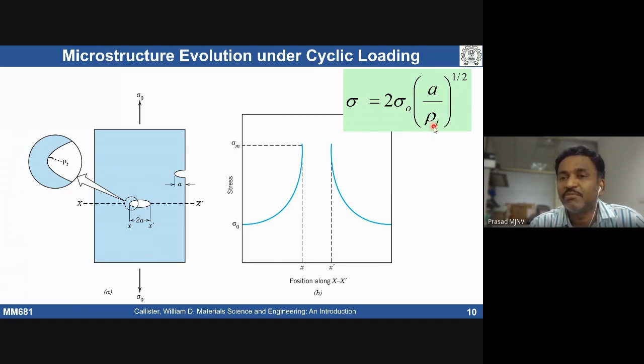So the sharper the tip, we do see the stress is going to be higher. That means if I assume the crack has been initiated or is already present in the material, it is bound to propagate, because we are going to see very high stress locally, and also locally a lot of plastic deformation can take place around the crack tip.